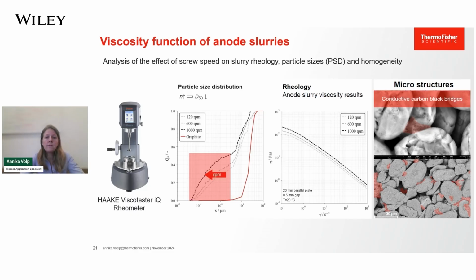We assume that this fraction corresponds to the carbon black, marked in red here on the SEM image. The extruder can break down carbon black agglomerates depending on the screw design and the screw speed. The right graph shows the viscosity of the sample anode slurries versus the shear rate. The change in size distribution is visible in the increase in the viscosity.